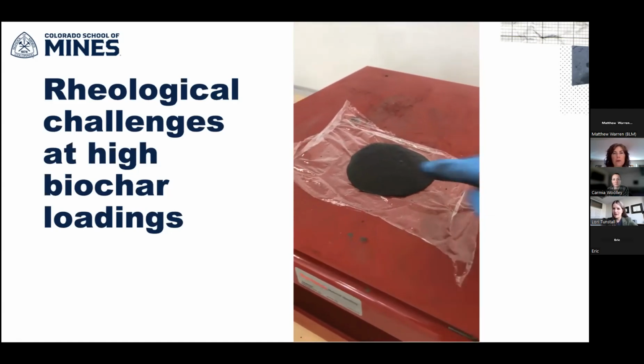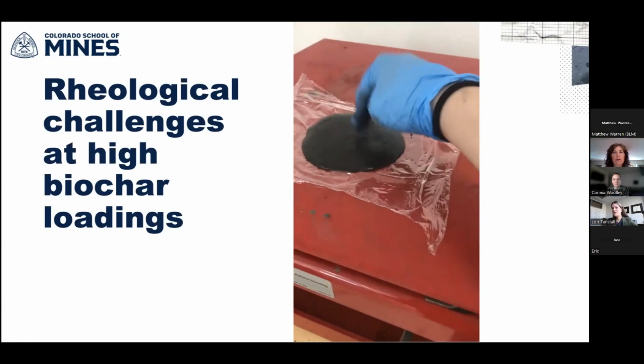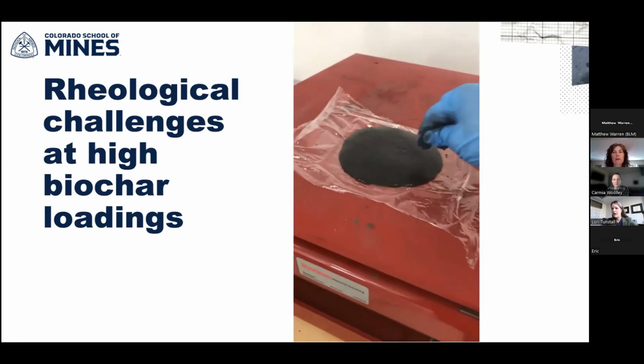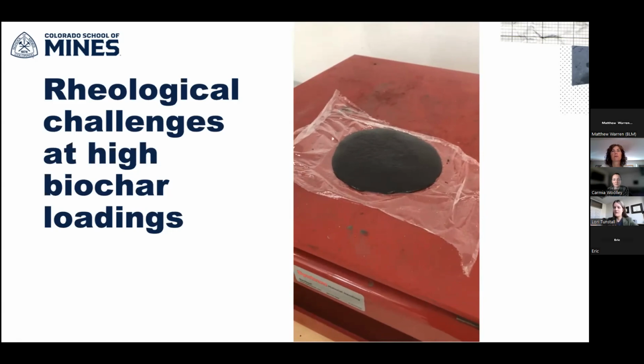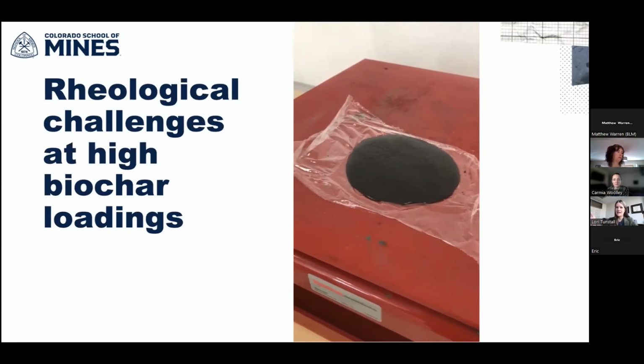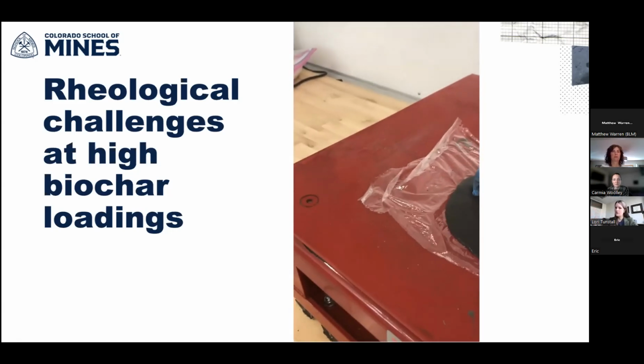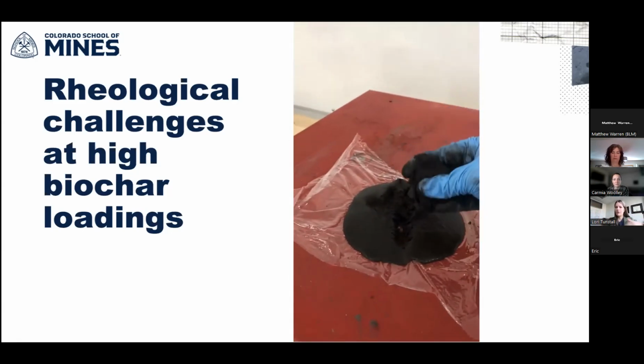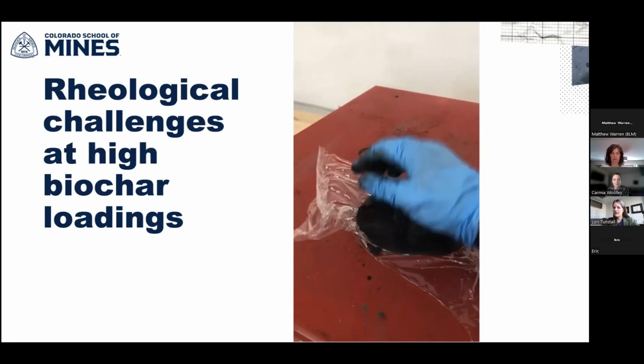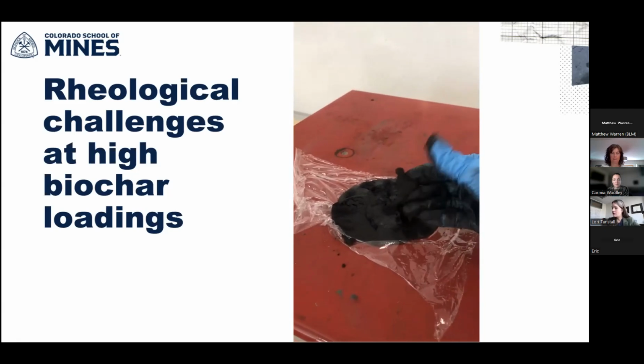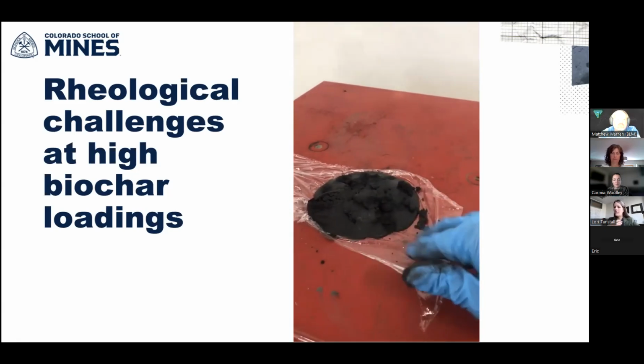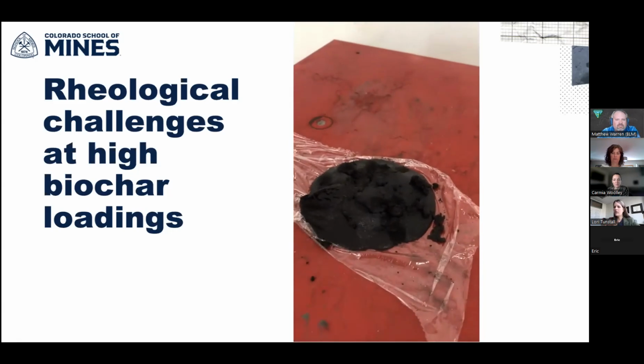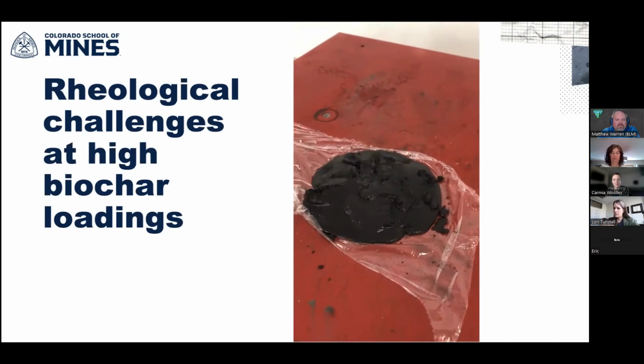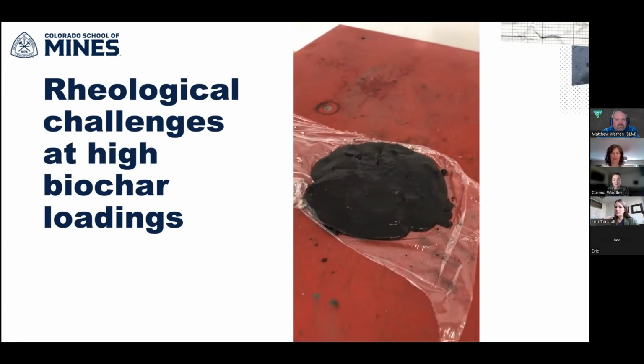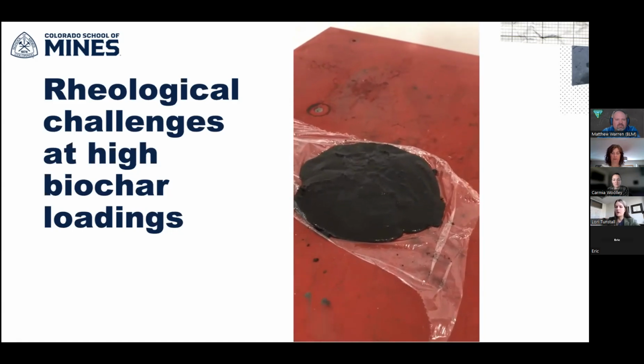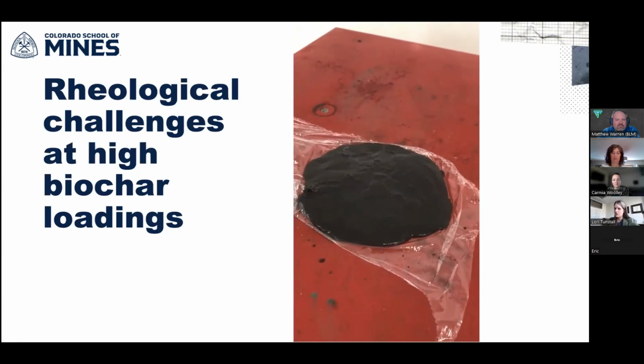Now, again, I am not an oil well expert, but I imagine that some of this could be beneficial or particularly helpful in that environment where you have steel caissons and you can apply perhaps vibration to it and get the material to flow. So I think for this application, it actually might not necessarily be a bad thing, and you could increase the loadings. Right now, for us, this has been a limiting factor for how much of the biochar we can incorporate into the mix, because at a certain loading, you get this kind of strange property, which doesn't work well for typical construction placement.